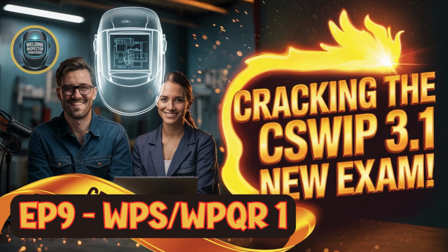Exactly. Third, the parent material type. Qualification generally only allows materials with the same material group number, which signifies materials with very similar chemical compositions and mechanical behaviors. You can't just switch to a different type of steel, for example. Got it. What else? Next, welding consumables. Production consumables typically must have the same European designation as those used in the test, meaning they're essentially the same chemical and performance family. The material thickness is also an essential variable. The test weld doesn't qualify all thicknesses, but a carefully defined range around the test piece's dimension. There's a limit above and below.